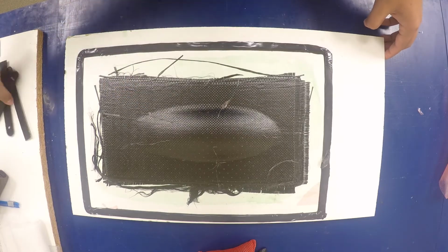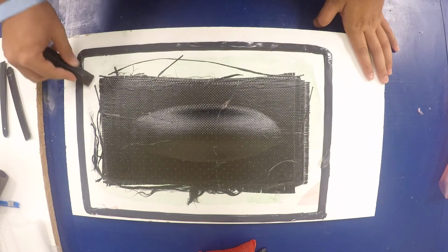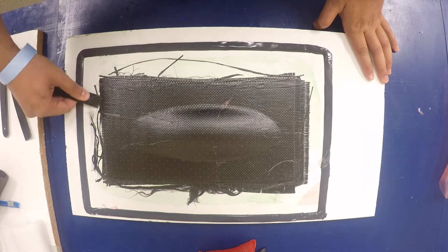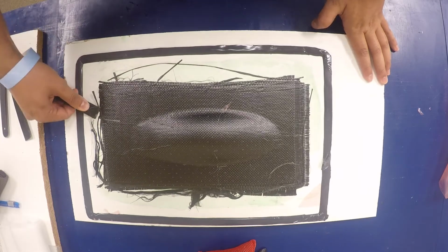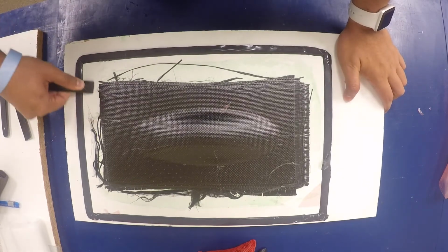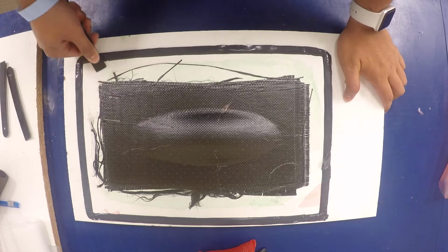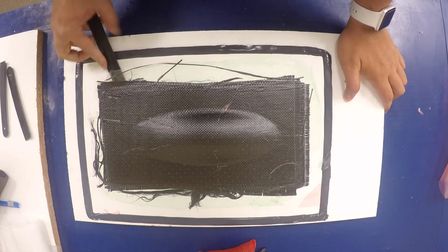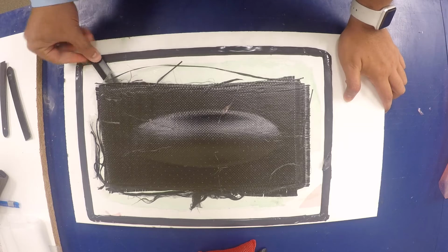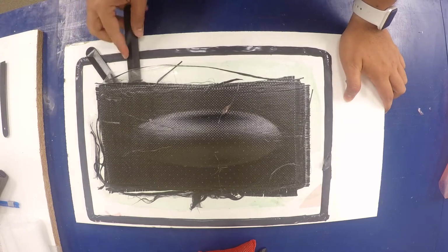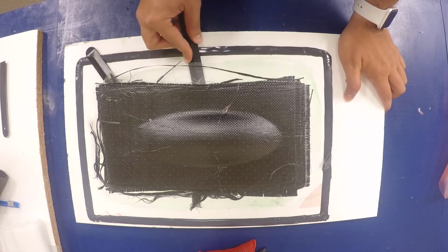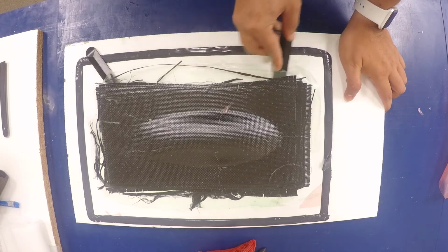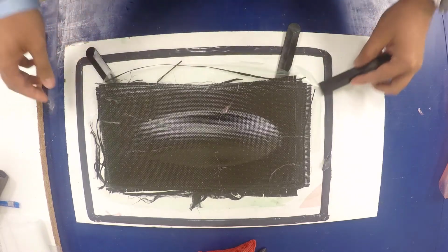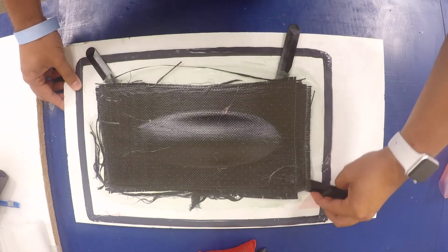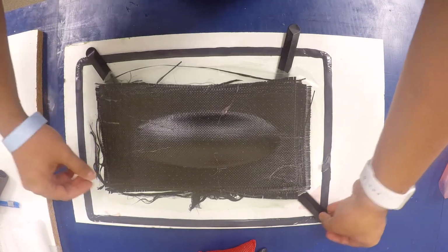We can now move on to removing the final product from the mold. If the release agent was correctly applied to the mold, the final product should just pop off after some effort. This process is easiest with some tools like plastic stir stick or plastic prying tools. Avoid using any metal tools such as screwdrivers or pry bars, as these will most likely scratch both your final product and your mold. This is especially important if your mold will be used more than once.